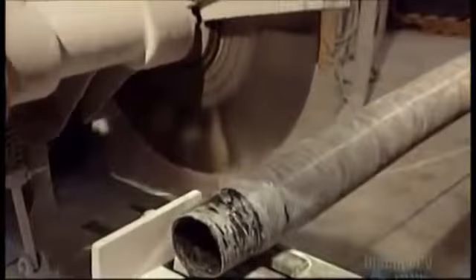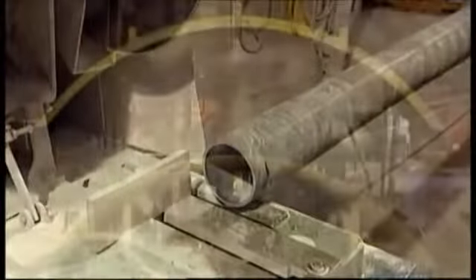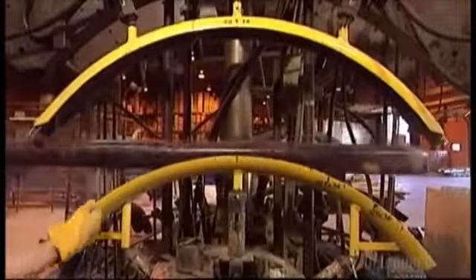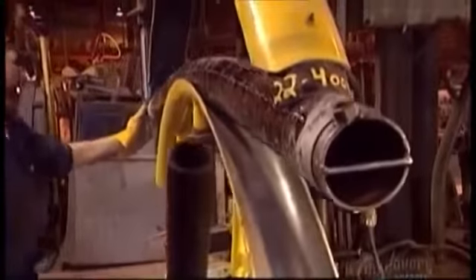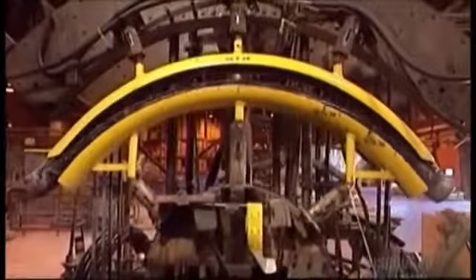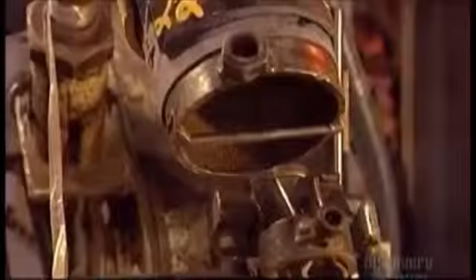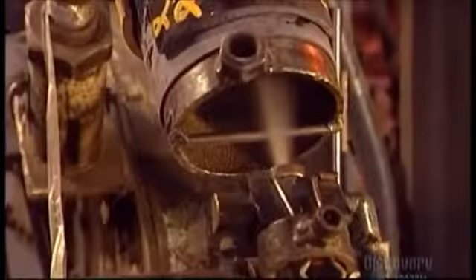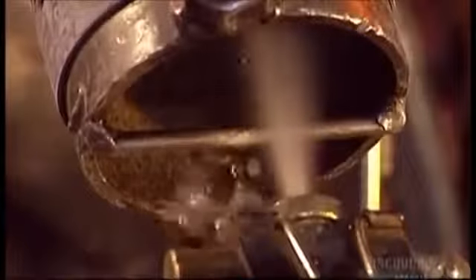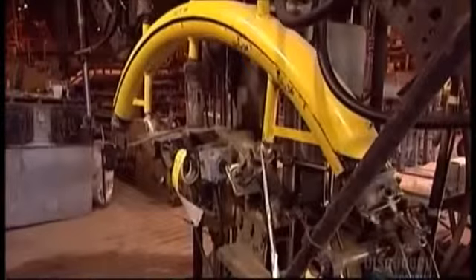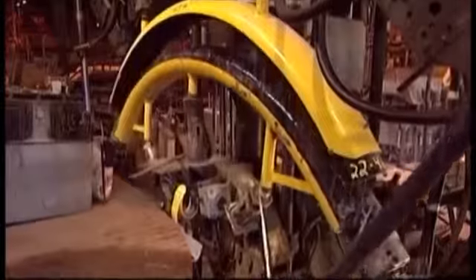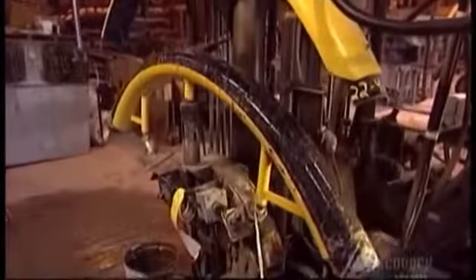Now a saw makes a neat cut at the top of the pole where the metal tenon will go. A tenon is the component that'll hold the light fixture to the pole. This particular model has an arched mounting arm. The composite has cooled a bit since curing, so they reheat it to make it flexible. After a bending machine makes the curve, they spray cold water inside to cool the material. This registers the curve in the resin's memory, setting the bent shape.